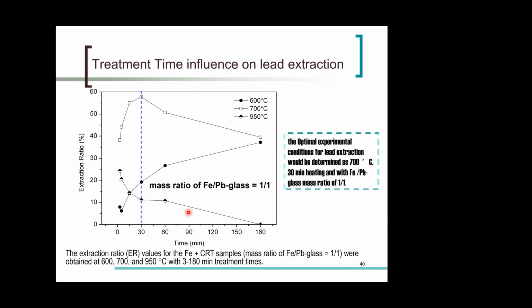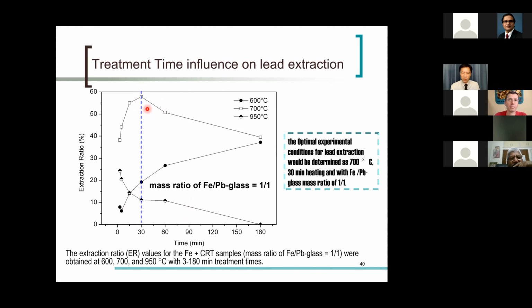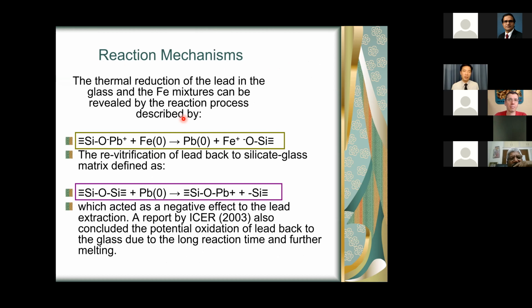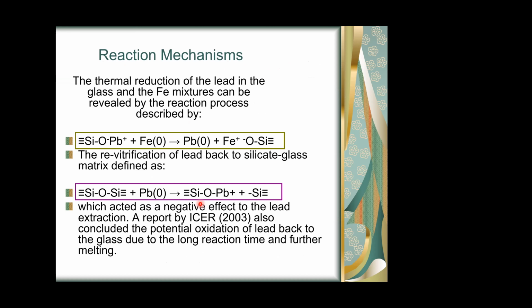Also, the timing. Because it is actually a very dynamic process at different temperature range. So in our case, corresponding to different temperature, say 700 degrees Celsius, the way we want, 30 minutes, that's enough. You don't want to get it too long because the unwanted process of the lead being reoxidized into the matrix will occur. So overall, in terms of mechanism, I think this is what we are most interested to find out, that you can have the lead to be reduced and have the metallic lead recovered, but you don't want this metallic lead to be further dissolved in the matrix. Overall system needs to be carefully investigated, quantified in order to have a good control of these techniques.